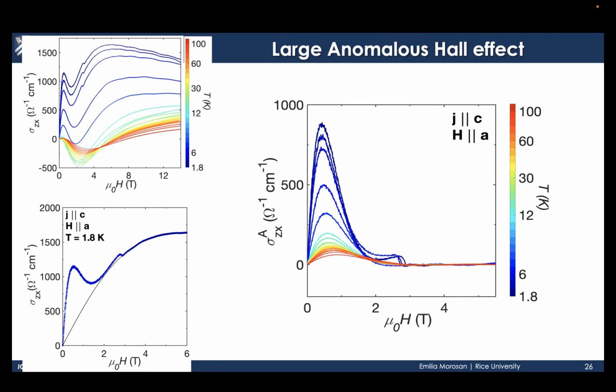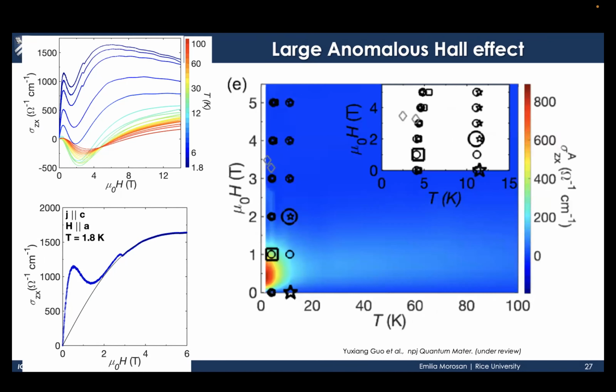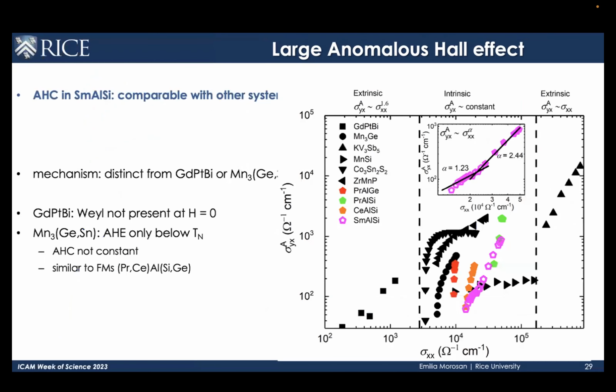All right, so what I wanted to say is that for the purposes of this discussion, what I'm looking at is the extra contribution to Hall that is not accounted for by band theory. But what's important for the point I'm trying to make is that even though magnetic order happens below 10 or 11 Kelvin or so, and we see some enhanced contribution from the Hall conductivity at very low temperatures over here, you may notice that this stretches out, as I showed in the previous plot, to high temperatures. And so it goes all the way from the antiferromagnetic state to the paramagnetic state. To some degree, this contour plot is very much like what was observed in gadolinium platinum bismuth.